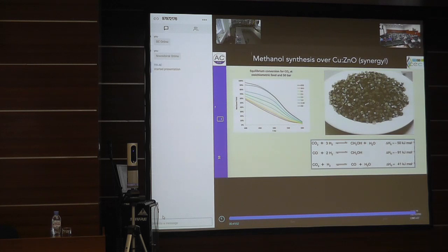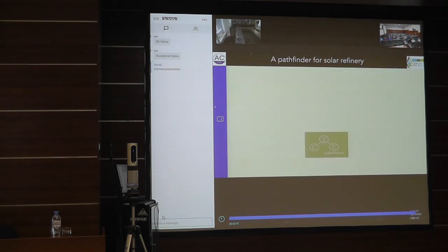And that falls down when you go to lower pressures, at 30 bar, where people would like to run the water splitting reaction, to about 1 kilogram of methanol per kilogram catalyst an hour. That is the productivity. And then you understand, under these conditions, you are really equilibrium limited. Now, I show you first a Pathfinder project. We try to do this in big, not only on paper.